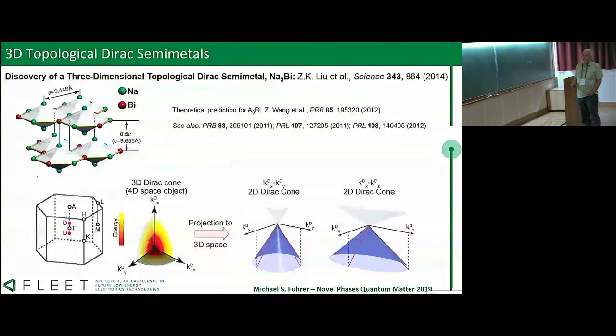The first such material where this was proposed theoretically is in the alkali metal 3 bismuth materials, sodium 3 bismuth, potassium 3 bismuth, and observed experimentally soon thereafter. So these materials have these hexagons of sodium bismuth, and then there are extra sodium atoms above and below each hexagon. So it's a somewhat layered structure.